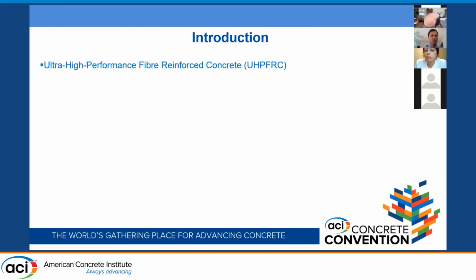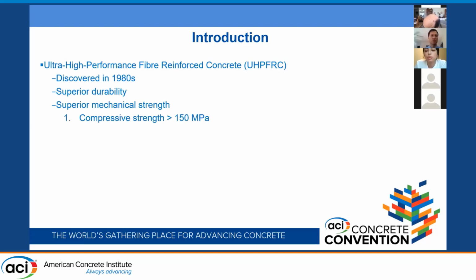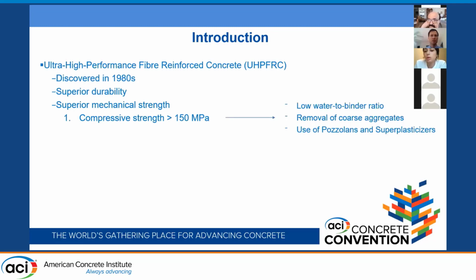So we all know that UHPFRC was discovered in the 1980s, and it's mainly characterized by superior durability and superior mechanical strength. More specifically, it's characterized by compressive strength that is typically in excess of 150 megapascal, and that is attributed to the use of a low water-to-binder ratio, removal of the coarse aggregates, which means removal of the weakest link in the concrete, which is the transition zone between the aggregates and the matrix, and the usage of pozzolans and superplasticizers.